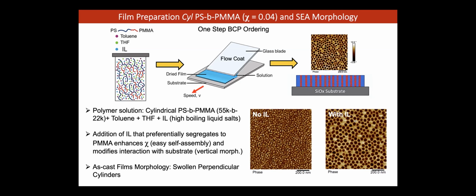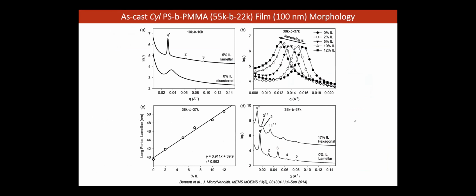We are working on this problem. A little more in detail: we are not the first to add ionic liquid for controlling block polymer orientation. Bennett et al. did some early work in 2014 and showed several really useful features. This first one, A, is a low molecular weight, 10K PS-PMMA. If you do the thermodynamics, you'll find that it is a disordered block polymer, because it is below the order-disorder transition, where chi N has to be greater than 10.5.